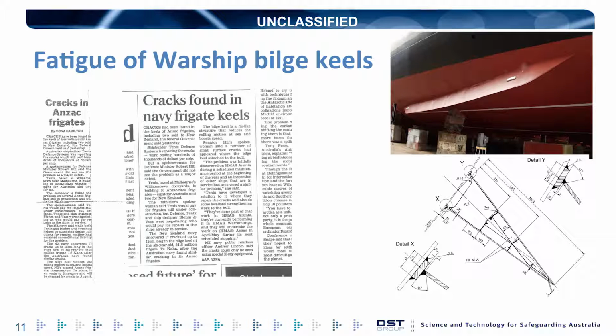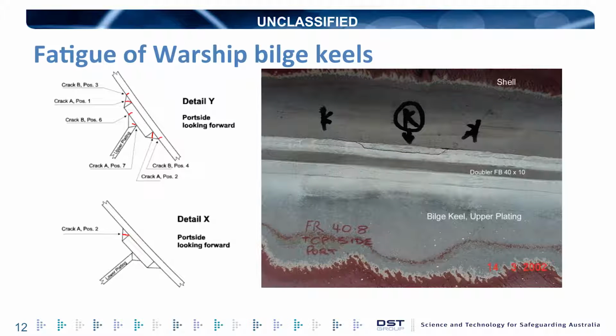And the newspapers told us that the bilge keels were cracking due to fatigue after about a year of service. And the issue was, why is this? You can see here some of the cracks were occurring at the welds between the doubler plate and the hull plate, and again between the upper surface of the bilge keel and the doubler plate.